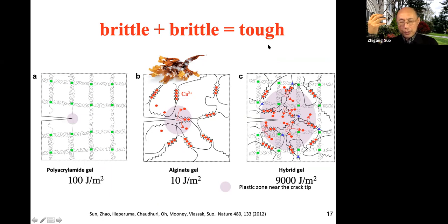Now, if you teach fracture mechanics, this will not surprise you. But it surprised almost all chemical engineers, chemists and biologists, who saw this as a black magic. This black magic has a very simple physical reason. So here's a crack. Before you break this polyacrylamide long chain, you unzip many of these calcium bridges over a very large volume, in our case over the centimeter scale. That's why you dissipate so much energy.